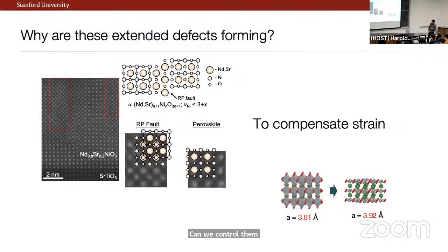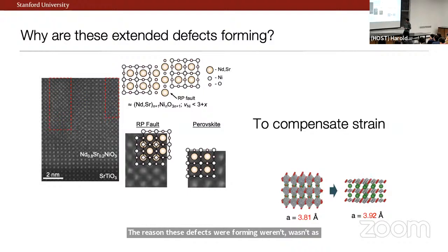I think I'm not pacing myself well, so I'm going to jump ahead and say, just in cartoon form, two things. The reason these defects were forming wasn't, as far as I can see, because we weren't very good at growing this system. The reason is that while we're trying to use this substrate to stabilize this material and this transition, the lattice was changing by about 3%, which is actually a very big scale. And so we were forming these chemical defects to try to accommodate strain in the system.